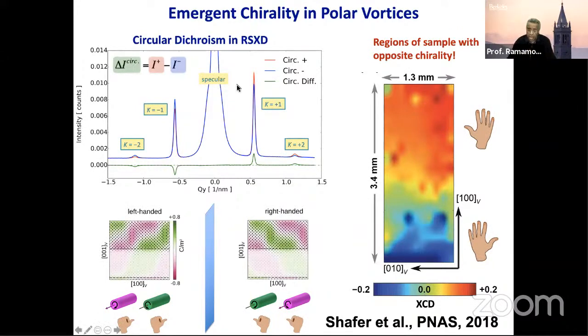And therefore, if you now image this as a function of spatial distribution, this is like a 3.4x1.3 millimeter sample. There are regions where the material is right-handed, and there are regions where it's left-handed. And in a few minutes, I'm going to show you that you can actually switch it back and forth between right-handed and left-handed chirality. So what have we done here? We have taken two materials, strontium titanate and lead titanate, put them together in a certain way, and created these vortices. And all of a sudden, the material where neither one of the parent compounds were chiral, the net material shows chirality, where I can also manipulate the chirality with the field to go from left-handed to right-handed.